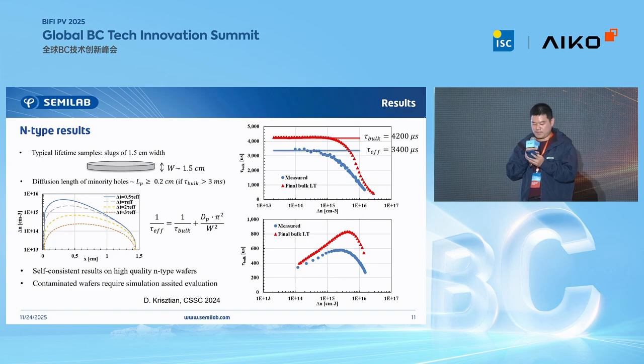When moving to N-type wafers, we investigate it on the 1.5 centimeter thick slugs, as it is used in the industry qualification. When we were doing this, we faced an interesting challenge. The 1.5 centimeter thick sample is not thick enough. It started behaving as a wafer during the measurement because the impact of the surface recombination gets stronger. And it resulted in that carrier lifetime was limited by the carrier diffusion processes at low injection levels.